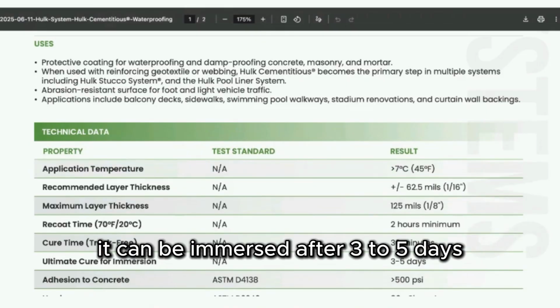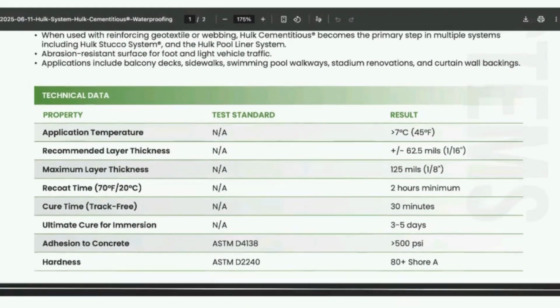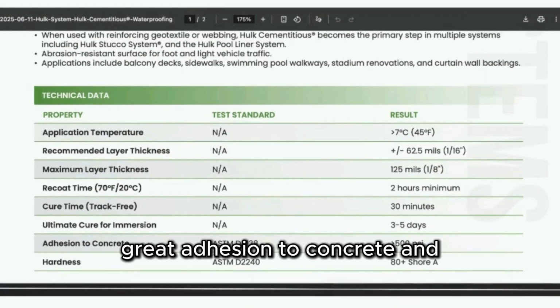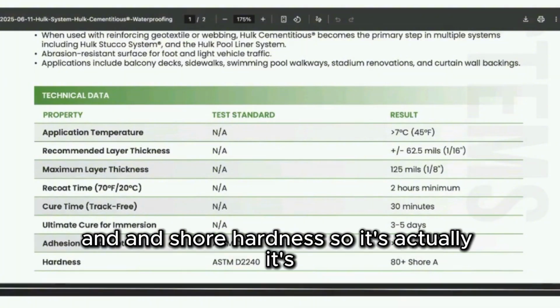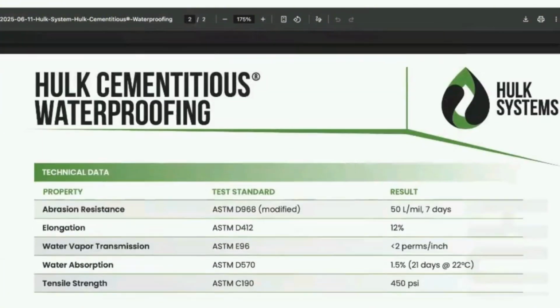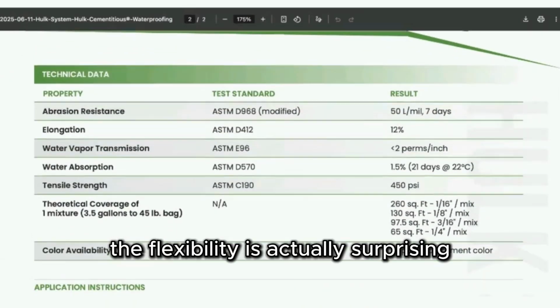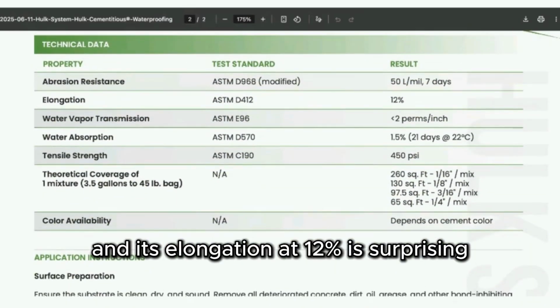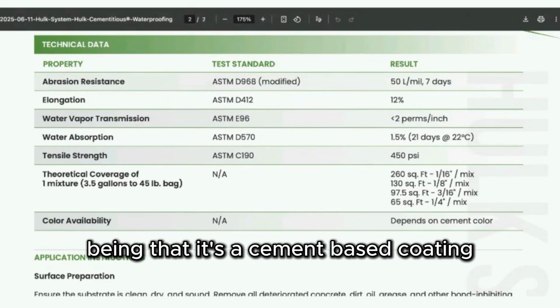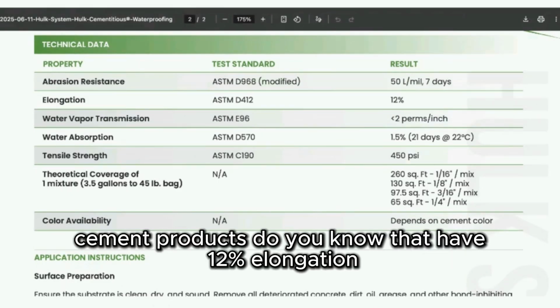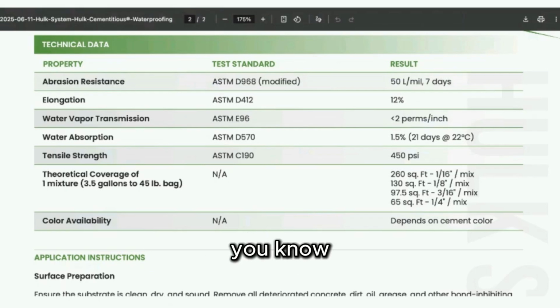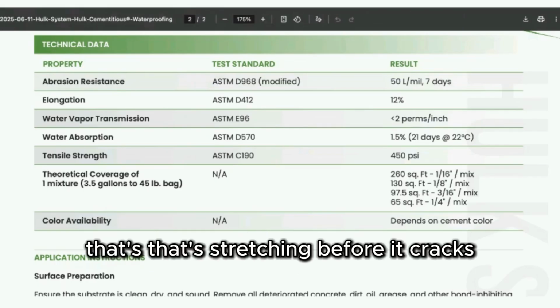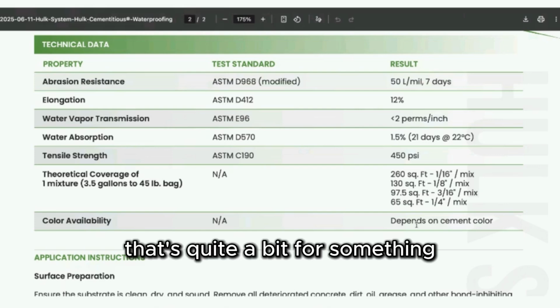It can be immersed after 3 to 5 days. Great adhesion to concrete and shore hardness. So the flexibility is actually surprising, and its elongation at 12% is surprising, being that it's a cement-based coating. How many cement products do you know that have 12% elongation? You know, that's stretching before it cracks. That's quite a bit for something.